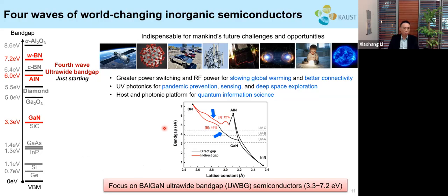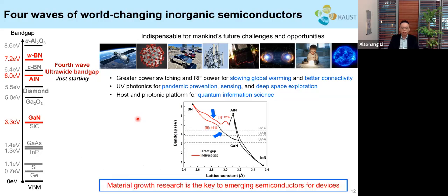So in our group, we have focused on the boron aluminum gallium nitride ultra wide bandgap semiconductors with a bandgap from 3.3 to 7.2 electron volts. Because of the infancy of ultra-wide bandgap semiconductor research, the material growth is really the key here, because without synthesizing good materials or materials with different compositions, it is not possible to understand the potentials of those materials for different device applications.